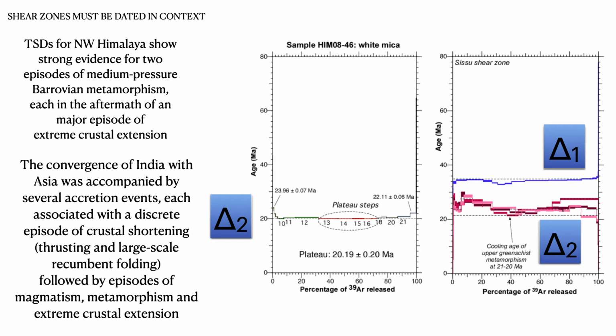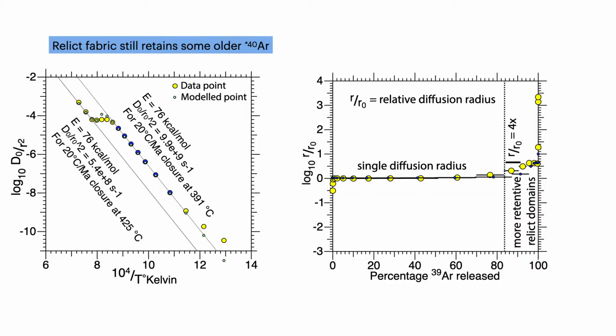But we can go further with the ultra-high vacuum diffusion experiments, the UHV diffusion experiments, and we were able to show that the muscovite in the main central thrust was a little bit more retentive than normal muscovite, and that the relict ages were held by the more retentive mica that degassed in the last 20%. And we actually have done thermal modeling using this data.